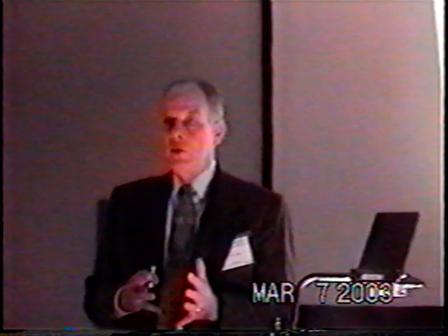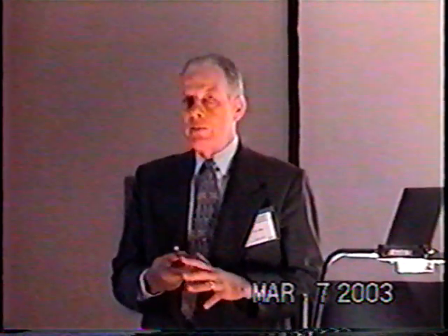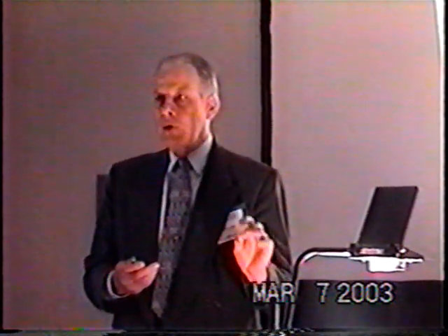The tiny particles approximate a fluidized bed. They do move around, they're always changing. We have a rather large effective surface area. We have these dynamic conditions that people believe are important for the cold fusion effect. And because we have so many particles, we're not dependent on the metallurgical properties of one sample of metal. We have many, many tiny samples, and you're more likely to get an excess heat effect. Because we find in many cases using solid samples that one piece of palladium will not work, and other samples will work. And here we sort of get around that major problem.